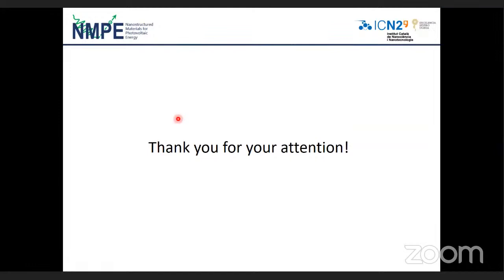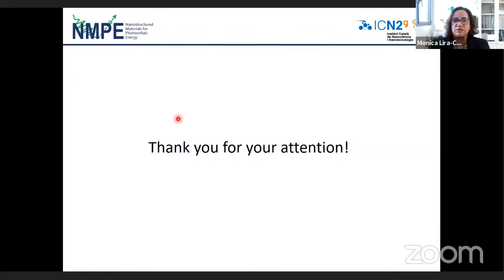Another question, asked by the same person, Shukdev Pandey: can experiments of 1,000 hours be reduced by studying some initial trend, modeling, or DOS simulation, density of states simulation? For us, the simulation is used to know the interaction between the additive and our Halide perovskite. I would recommend, if you want, you don't initially need to do 1,000 hours. You always compare the reference without additive and with additive, and you need 10 hours. If these 10 hours are good, you can keep going. If not, of course, stop this stability test.